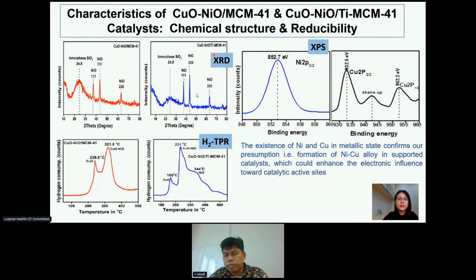Okay, so for the TPR analysis, the reducibility patterns of catalysts, especially for this modified silica support, are slightly different from the pure MCM41 catalyst. Okay, it shows that there are three reduction peaks present in the analysis, and the reduction peaks indicated that there's a presence of the strong interactions between the copper oxides and also the nickel oxides, which leads to the shifting of both peaks, which is the copper oxides and also this mixed copper nickel oxide, and they shift to a lower temperature, okay, as compared to the catalyst without modification, where the reduction temperature is higher.